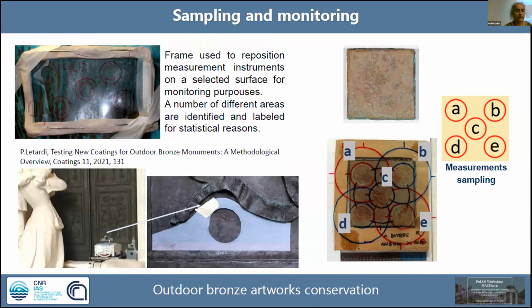The other point is the sampling, because obviously you cannot map all the surface of this very big object. So you need to define a way to make relevant sampling, and as the definition of the different measurements is not so precise, as I will tell you in a short time, the best way is just working by comparison. So you make measurements before the cleaning, after the cleaning, after the treatment, and after some time that the treatment has been applied, and you want to characterize how it's evolving.